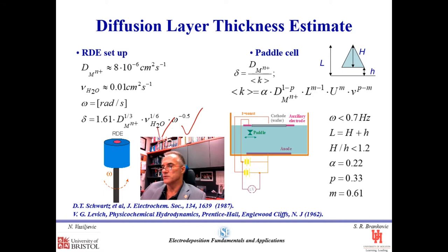The other definition here shows the diffusion boundary layer thickness as a function of the kinematic transport coefficient K, which is defined in terms of the geometry of the paddle cell, which is commonly used in magnetic recording or microelectronic applications in industry. Depending on the geometry of the paddle, which has typically triangular shape, which goes in a linear motion back and forth across the wafer surface at a certain distance h, with a certain geometry h capital and overall height l, then we can define this kinematic transfer coefficient, and as a function of this coefficient, we can define also the diffusion layer thickness in the paddle cell itself. More elaborate discussions of both approaches are given in these references.